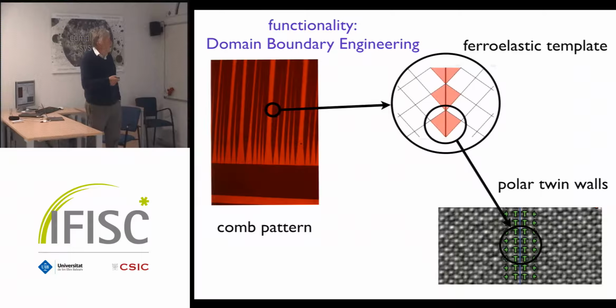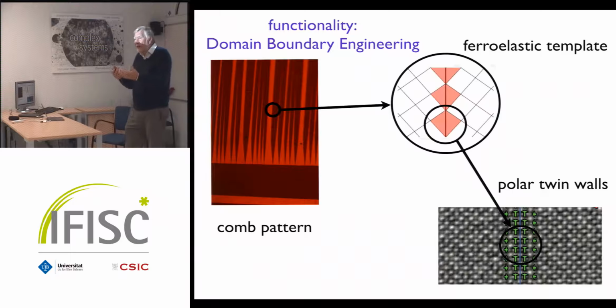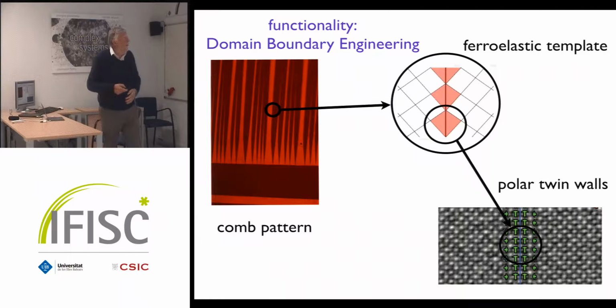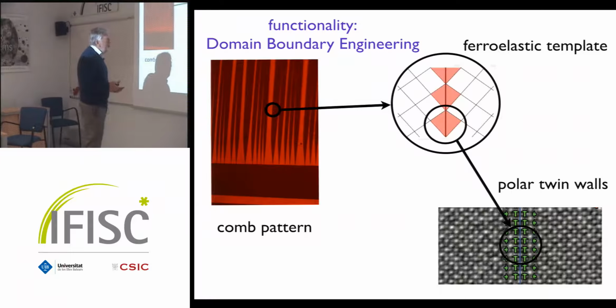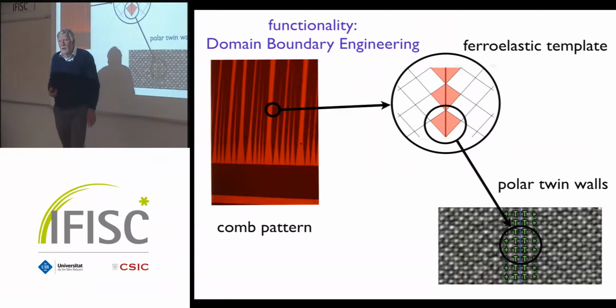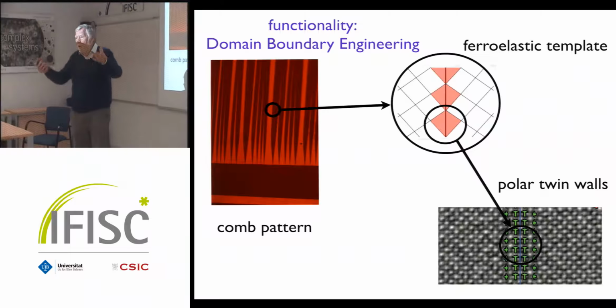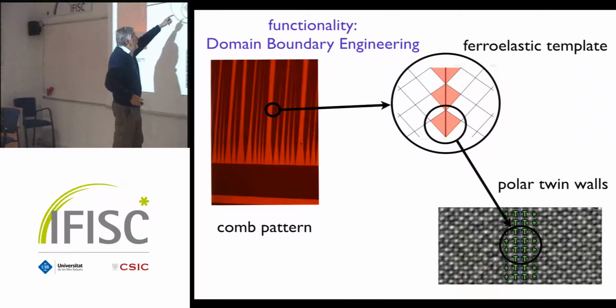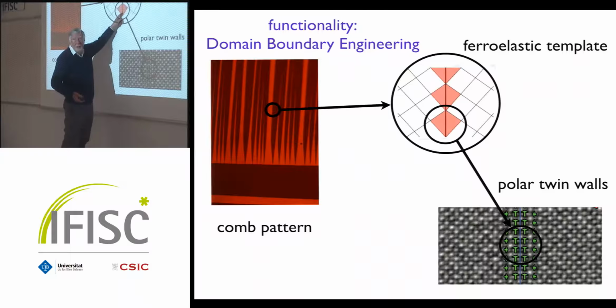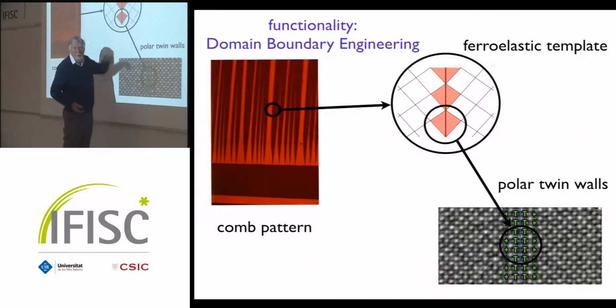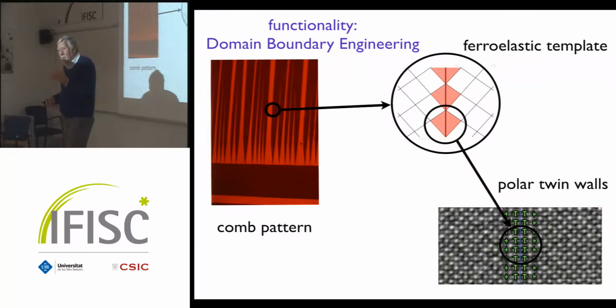Here you have a picture of these domain boundaries, okay? Then you magnify what is here, and that's how they geometrically have to look like, because you have something in that direction, you have something in that direction, in the middle you have a different unit cell. So the atoms have to arrange themselves somehow to fit into the pink area here. Now what you immediately can say is that these ones are rectangles and these are kite-shaped. So there, if there's an atom in the middle, there's absolutely no reason why it should move anyway. I mean, all directions are almost isotropic. If you are here, then you can clearly see there's a bias in this direction, either up or down. Either the atom is too big or it's too small, but it doesn't want to be in the middle. And that's what it is. It doesn't want to go right or left because that's symmetrical. So it's just a very simple symmetry argument.